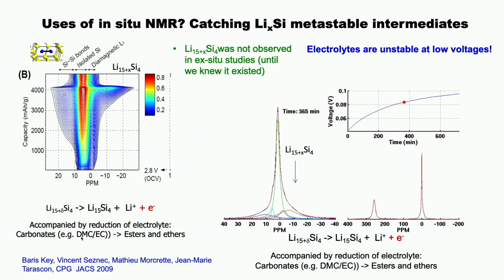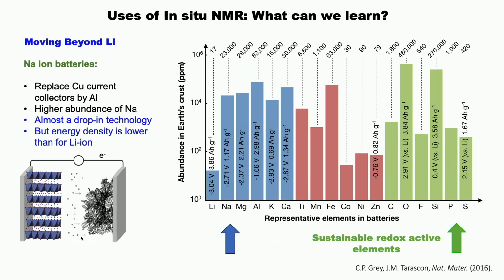But what we showed in this very simple study was that if you took the fully lithiated silicon and just let the system rest, you could watch the open circuit voltage go up, which means there's a reaction happening. And by looking at the NMR in situ, you could see the peak disappearing as this material was being oxidized by the electrolyte. So the electrolyte is being reduced, and the silicon itself is being oxidized. This was the first study to show that the problem with silicon was not per se the large volume expansion as it reacts with lithium, but that it didn't form a nice passivating layer on top of it. That's what forms in graphite, it's called the SEI, and that's why all graphite materials actually work.